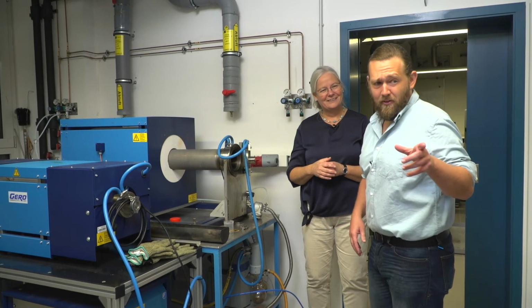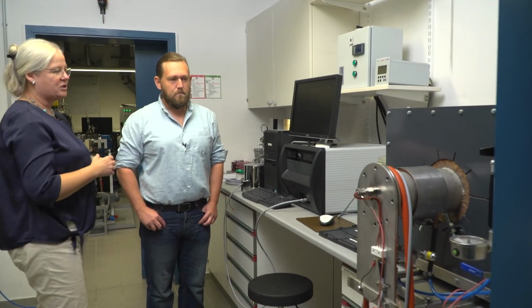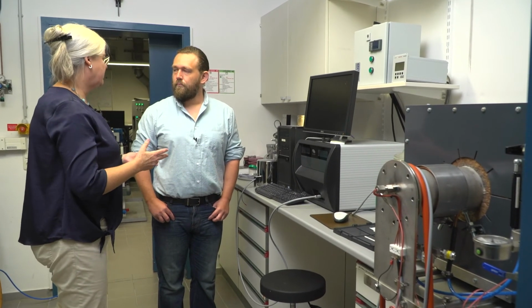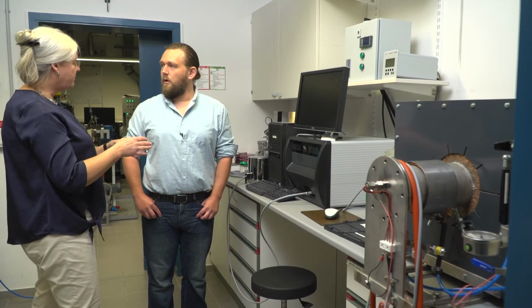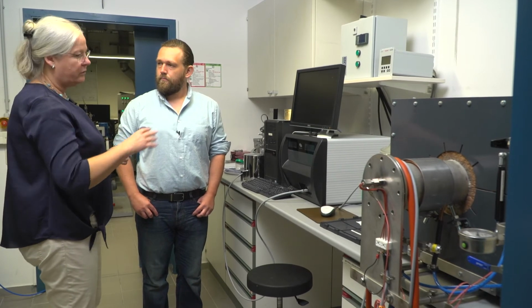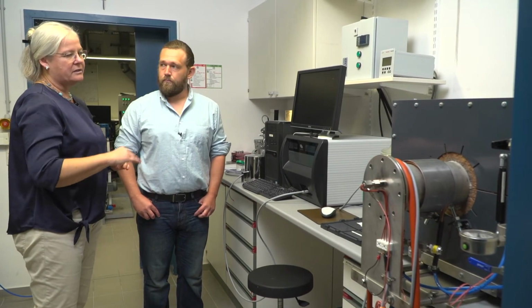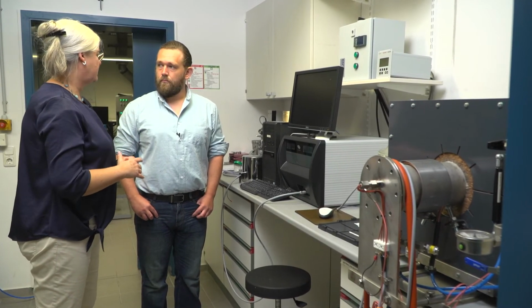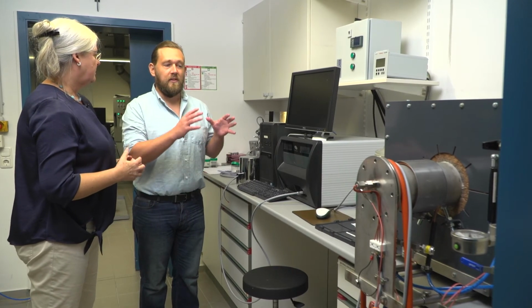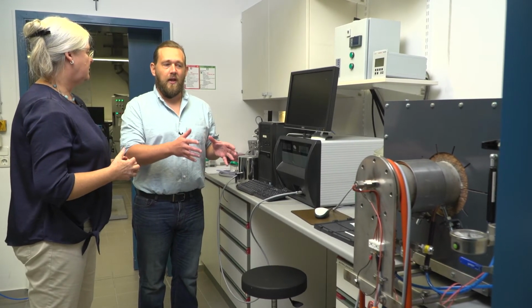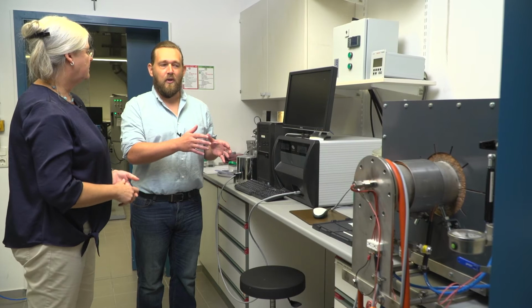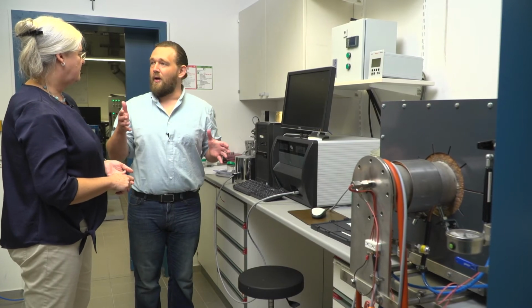And so over here, there's something that looks like a smaller tube furnace. Is this for making carbon aerogels too? No, this is a furnace for the hot disk measurements. So if you would like to have hot disk measurements or thermal conductivity measurements, not only at room temperature, but with higher temperatures, you can use this furnace, and it's up to 400 degrees Celsius. So this machine tells you how good of an insulator an aerogel is and how its insulating properties change as you go up to higher temperatures?